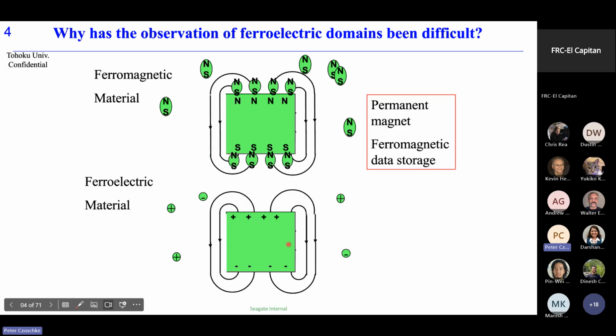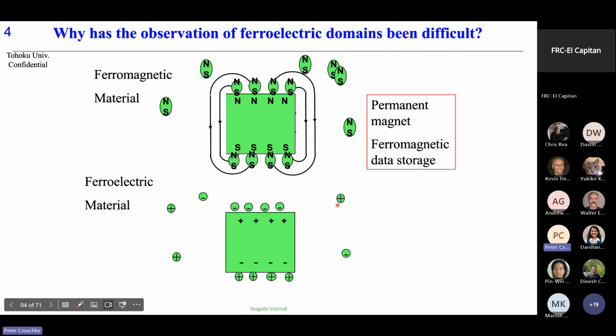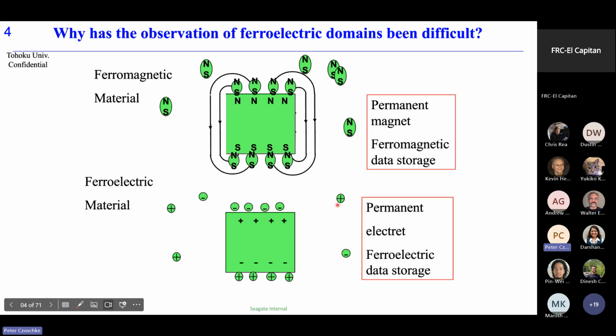But the ferroelectric material also has a dipole moment, composed of positive charge and negative charge. And as you know well, charge exists as a monopole. So in the thermal equilibrium state, the outgoing field is screened completely. This is the reason why there is no permanent electret. As a result, ferroelectric data storage is quite difficult, because if we approach with some electronic detector, we cannot recognize the state inside the ferroelectric.